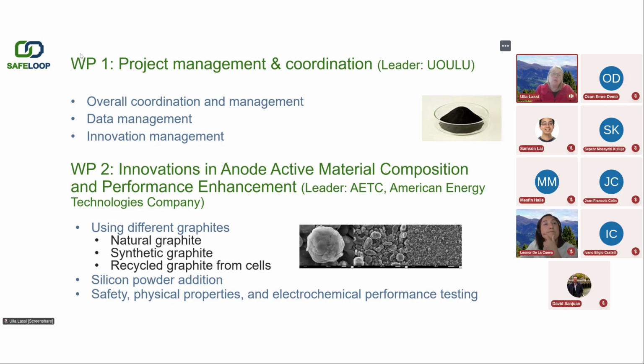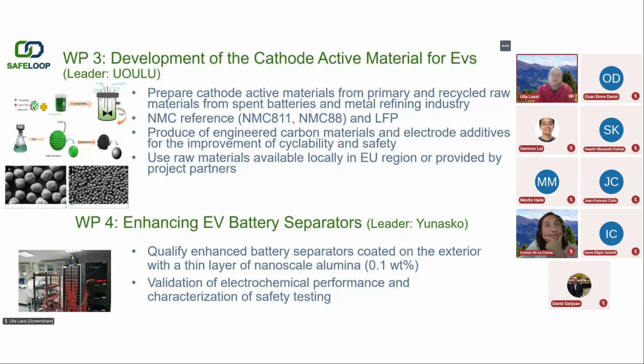Personally, I know best WP3, where we develop the cathode active materials for EVs, and this is based on the use of recycled content in material flows. In the laboratory scale, using quite a big reactor scale, something like 5 to 6 liters, we will co-precipitate those precursors for batteries and then lithiate them to get nice or less nice spherical particles. Our focus in the project is NMC 88 chemistry, but we also use other chemistries, mostly NMC 811 as a reference material. And here we use not only recycled elements, but also conductive carbon additives, which are also materials from recycling.